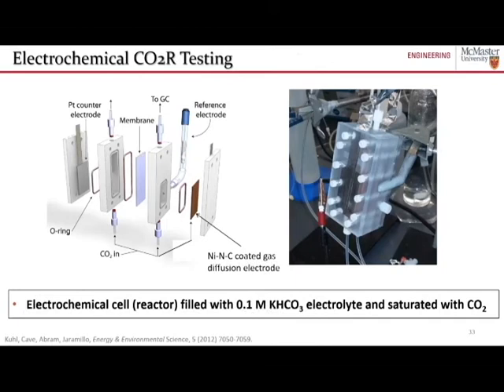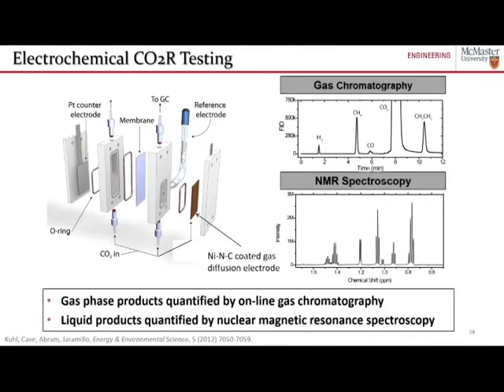The CO2 coming out of the electrochemical cell was fed to a GC, where we were able to detect and quantify the products of the CO2 reduction reaction in the gas phase. So things like hydrogen, which is the competing reaction that we want to shut down as much as possible. Things like methane, things like carbon monoxide, and things like ethylene. Today, I'm going to particularly be focusing on carbon monoxide, but this is ultimately how we test all the different materials in our lab to see what the array of products being formed on them is.